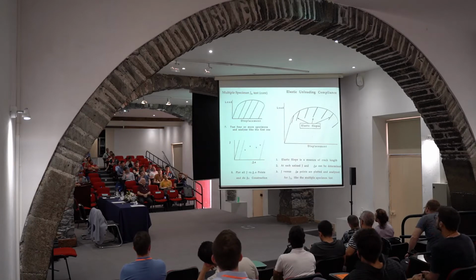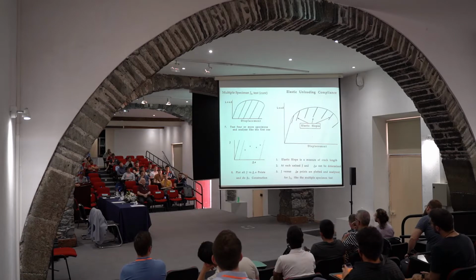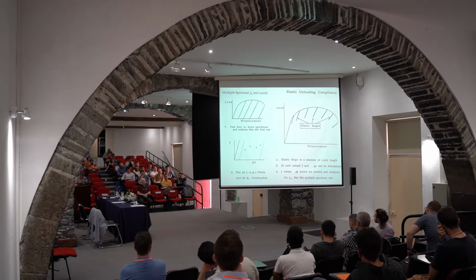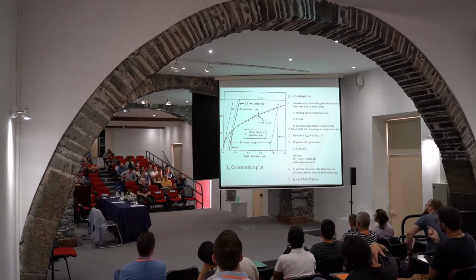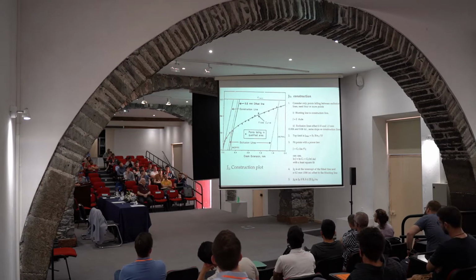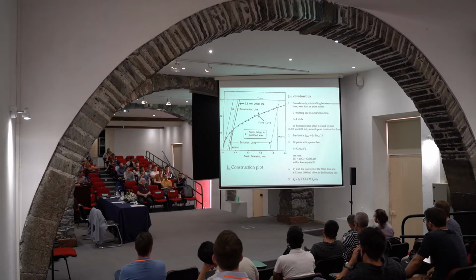This difference between single and multiple specimen is shown here. You can see to the left at the bottom those at least 4 points needed for multiple specimen. That means at least 4 specimens, which is really not practical. But then once Paris and Rice noticed that elastic slopes can be used as the so-called unloading compliance technique to actually monitor crack growth, then the single specimen technique was all set to go. So this is one recorded JR curve, and from that curve we can extract one of the most important parameters. This is J1C, that is fracture toughness, which can be correlated with K1C, and there is a procedure for how one should do that.